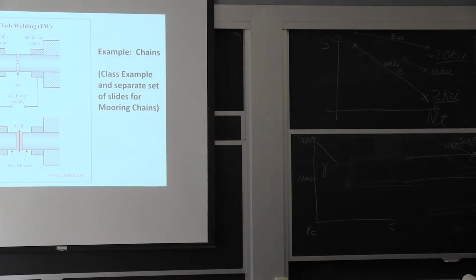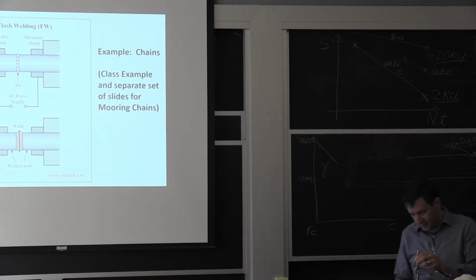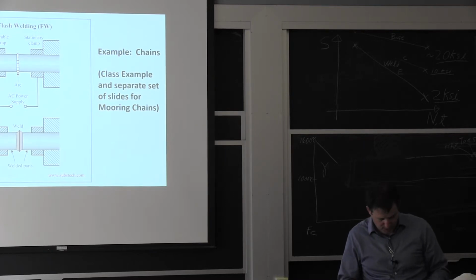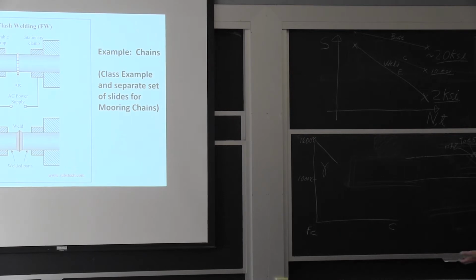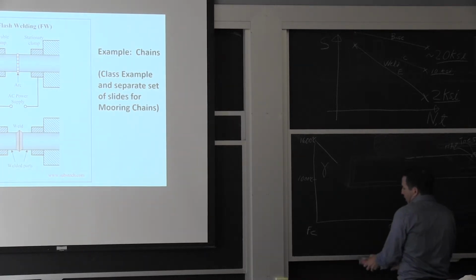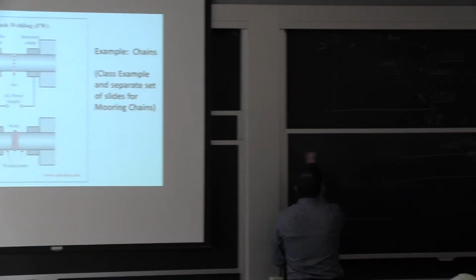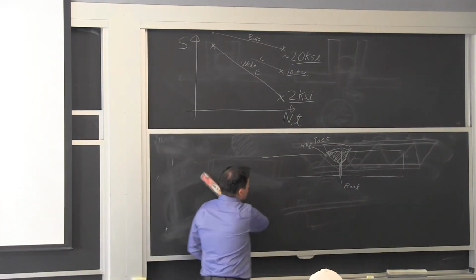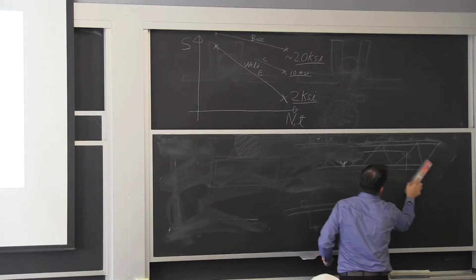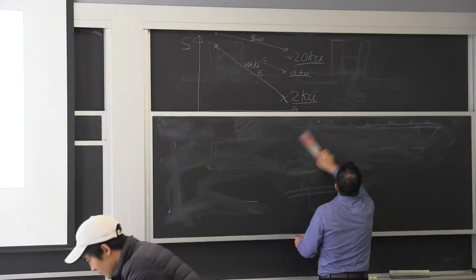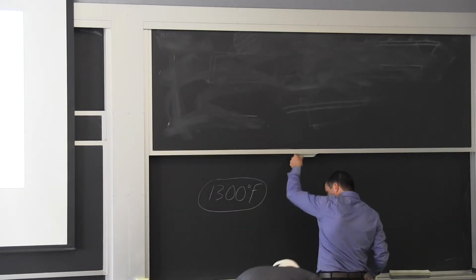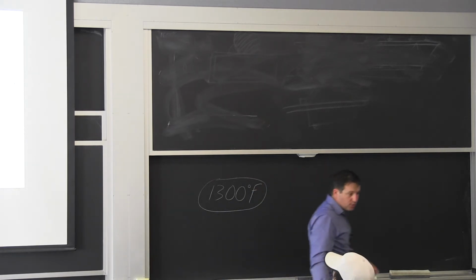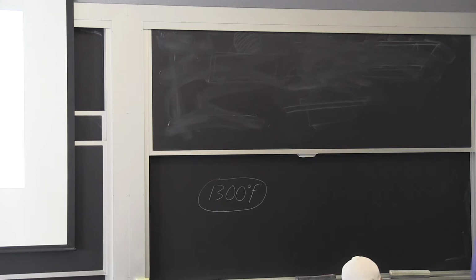All right, so chains. I was thinking about it over the weekend. This is a lightweight one. This is an aluminum alloy, and you can see on the one side you have a weld. The other side doesn't. So it's made of short segments, and you start with a round straight bar and you start bending it. A lot of times you'll get the alloy warm, so you don't cause too much distress, or you don't induce cracking when you make those bends. I've seen this done on very small chains, but also on huge chains, and we'll see that in a minute.